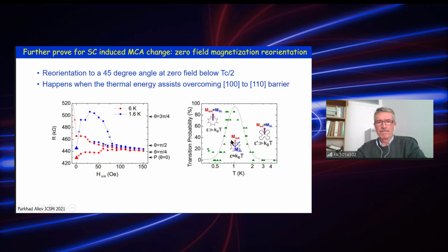Also, we can even observe orientation at 45 degrees at zero field — spontaneous orientation. This is observed at some intermediate temperature. So our experiments also show the change of magnetocrystalline anisotropy is due to the spontaneous rotation of magnetization.